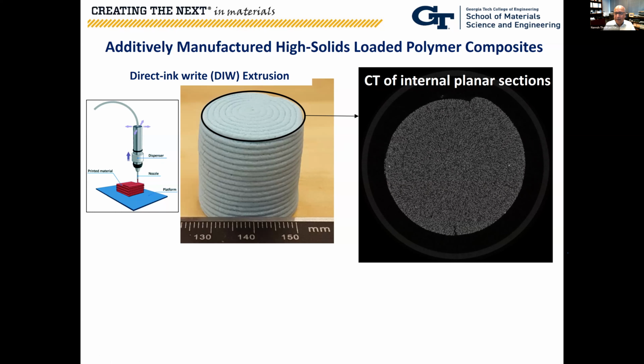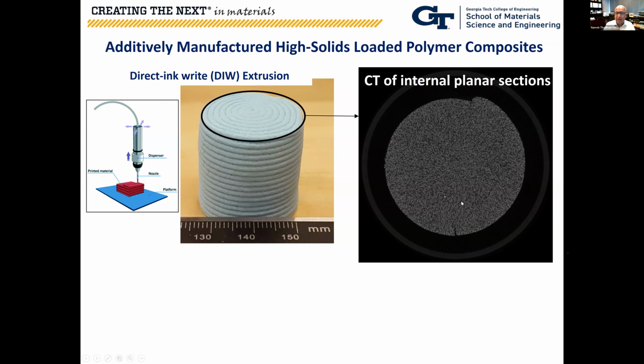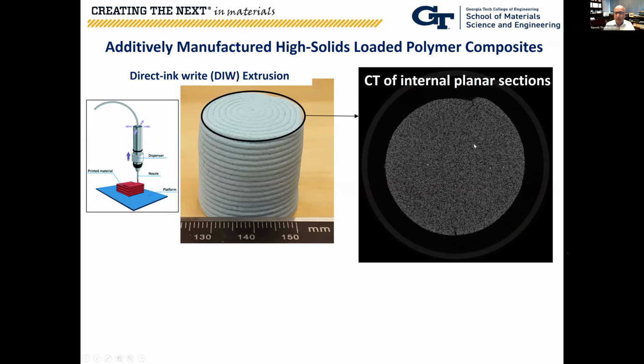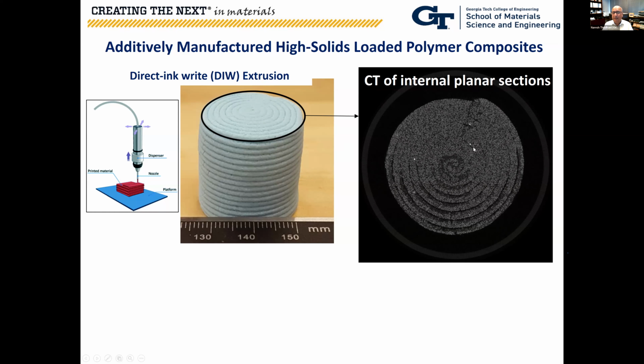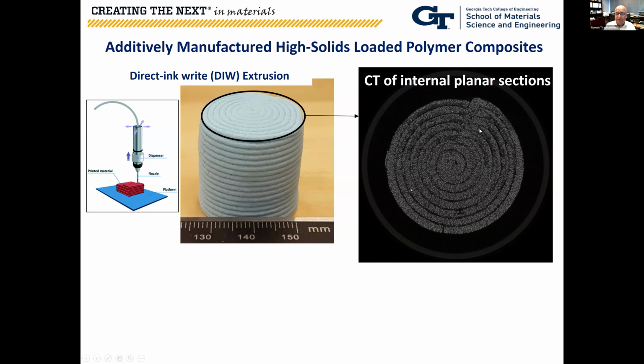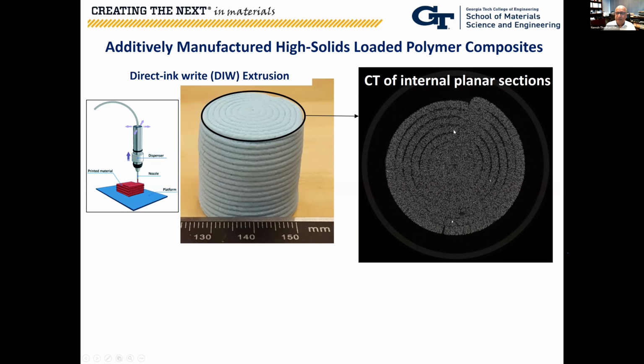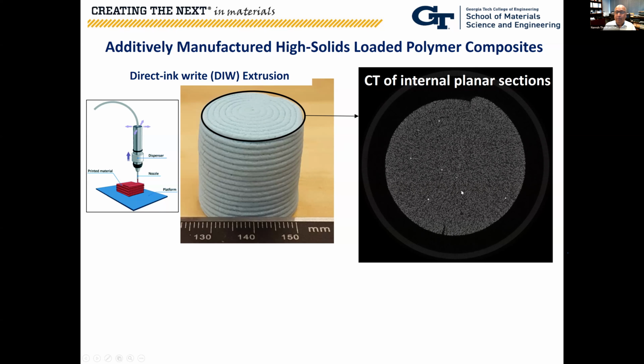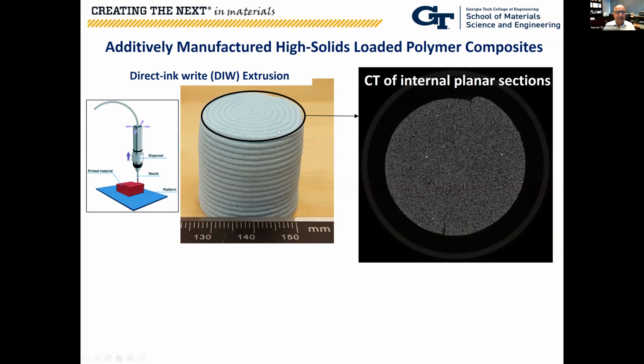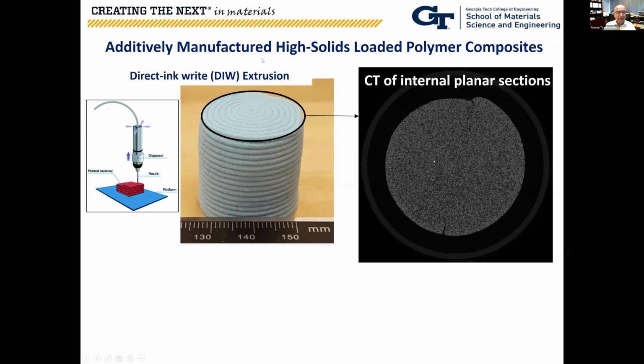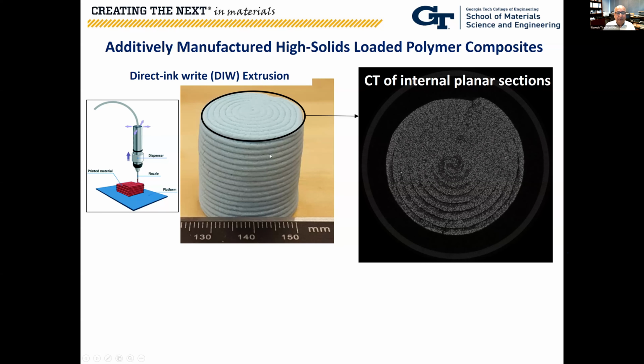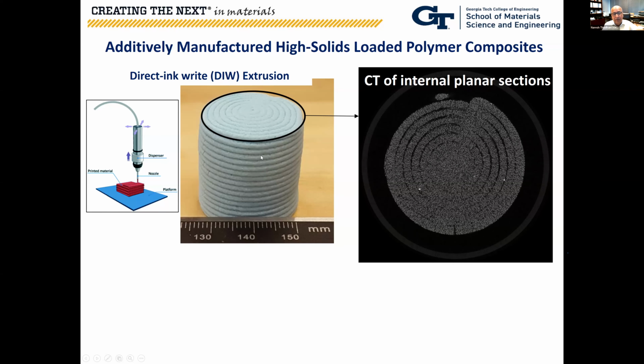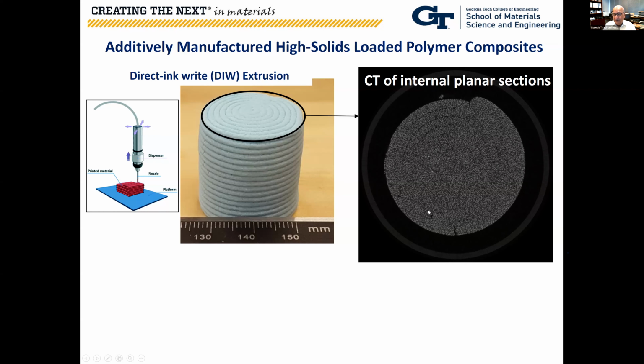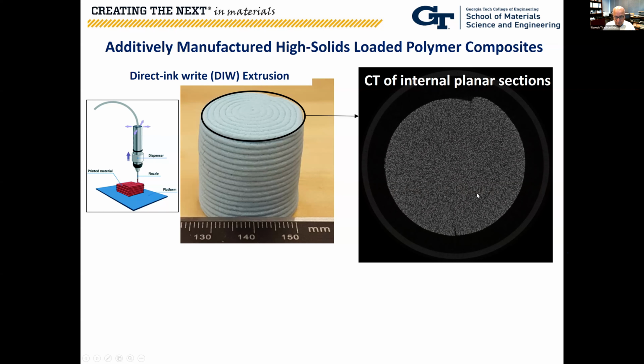The particulate contrast that you are seeing is coming from the presence of those solid particles, and the dark regions you are seeing are the openings between the different filaments, as you can see along the surface, or as you go layer by layer, and you can see how those are evolving through the thickness.